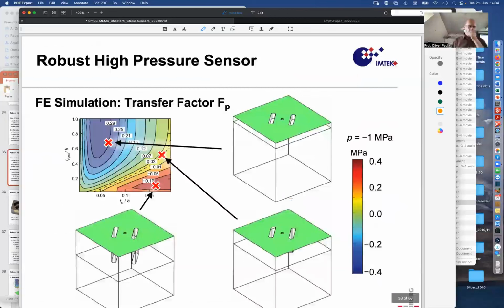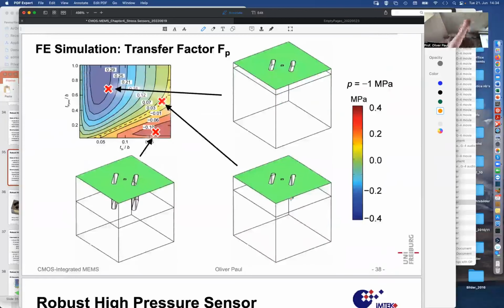And so one question was how to divide that space into glass and silicon. Should the glass be thin? Should it be halfway thin, or should it be thick? And so this structure with a thin layer of silicon, let's think about this layer being very thin, bonded to the glass. If it is very thin, it will not oppose any effective resistance against the contraction of the glass. If the glass is forced to compress under an isotropic pressure, it will just pull the silicon along because of the little material that can counteract that. And then you essentially have an isotropic compression of that silicon layer from the sides.